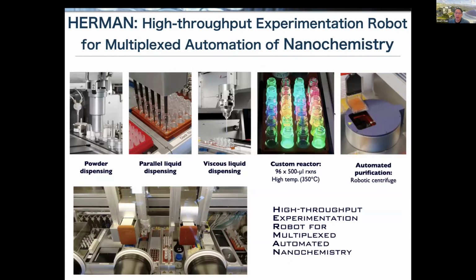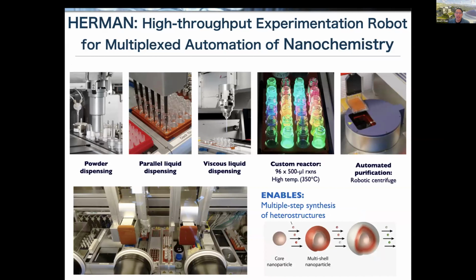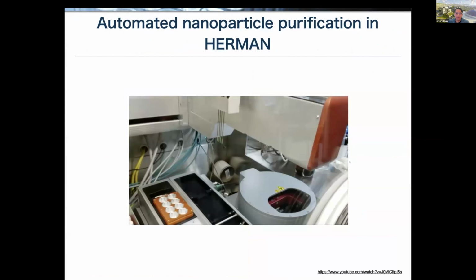And the multiplex comes from the fact that instead of doing these reactions one at a time in an 8 reactor array, which isn't that high throughput, we in fact have a microplate reactor that can now react up to 96 different nanoparticles in parallel. So in addition, it has bells and whistles such as powder dispensing and viscous liquid dispensing. And importantly, it has an automated centrifuge.